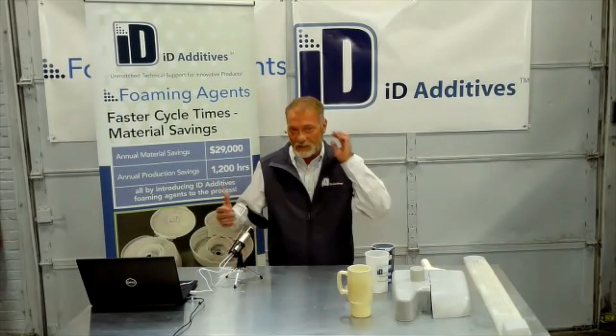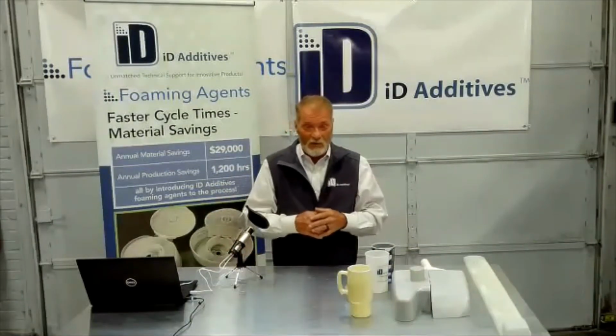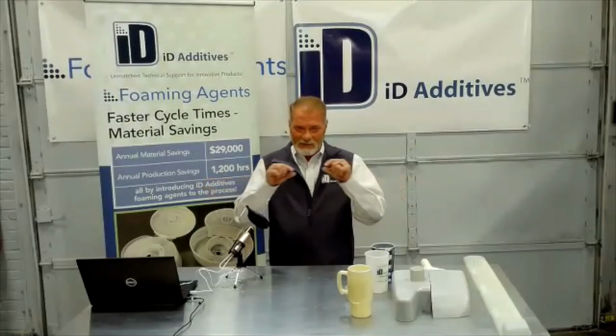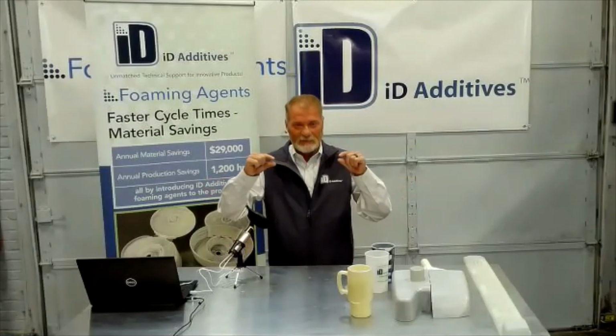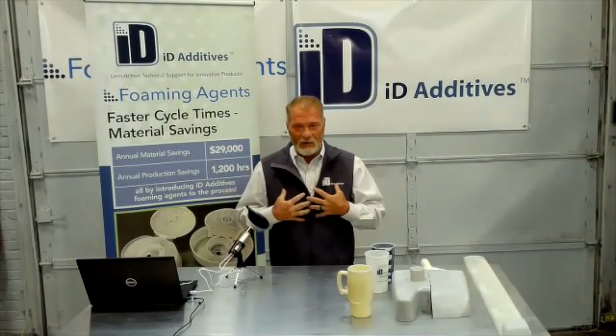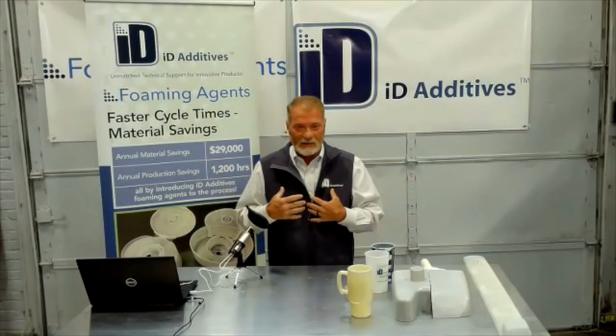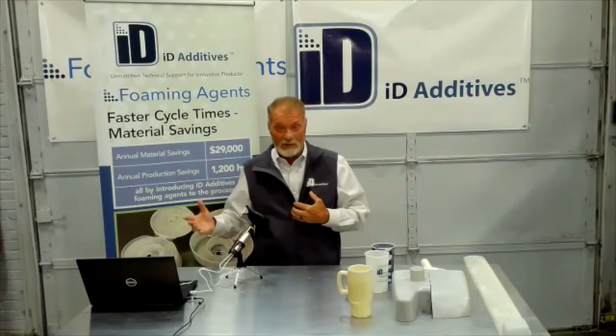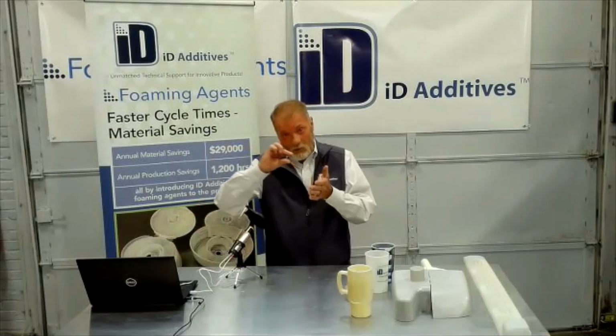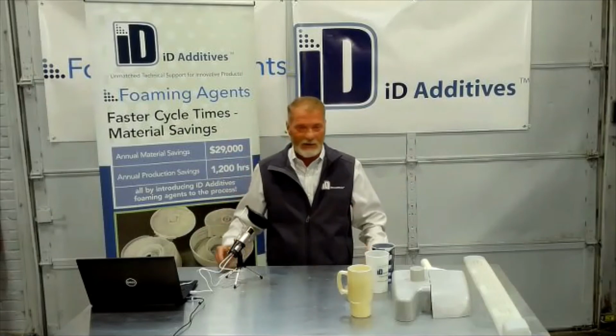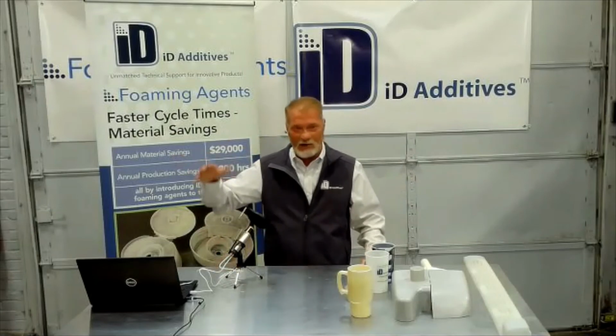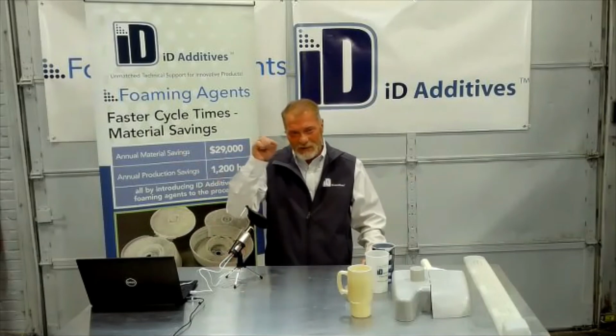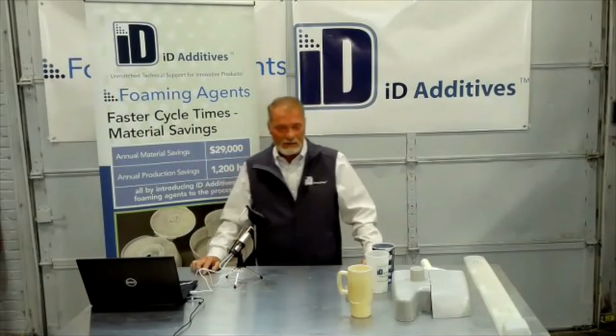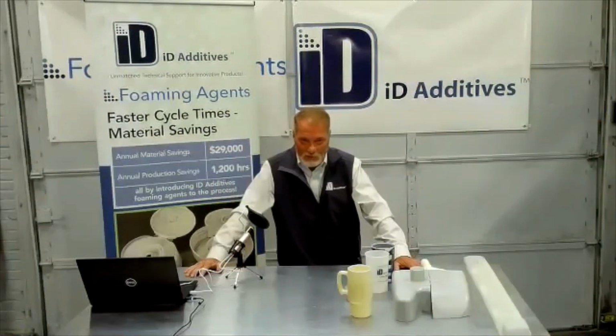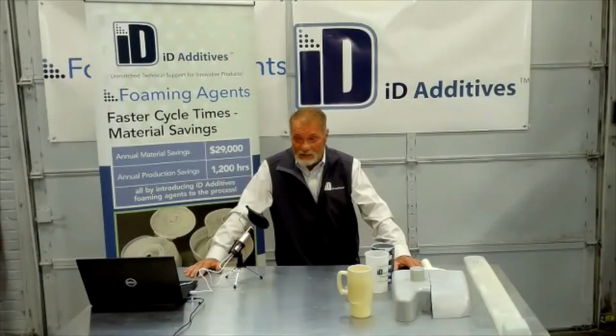It used to be just drop it in and inject slow. Well, that gives you all the splay, but doesn't necessarily mean you get all that foam in the middle. And that's what I call a foam part. Just because it has splay doesn't mean it's foam. It just means you added foam. But when you cut the part and you see that foam core, now it's foam. I've cut parts where splay was everywhere, and there was only a little bit of foam here and there. So that process is super important when it comes to foam, to make sure that you get it in quick and get off of it.